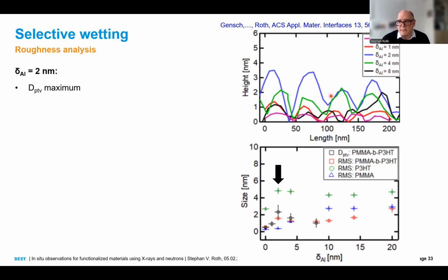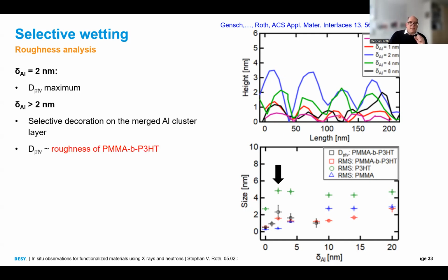And you see here when there is no aluminum on, you have this pink line. Then you start to deposit aluminum on, and you see that basically the aluminum reproduces the roughness of your substrate, and it goes even up to 2 nanometers, and from 4 nanometers you see that this roughness reproduction goes down and down until 8 nanometer. So actually what is happening is that aluminum goes selectively to one part of the diblock copolymer.